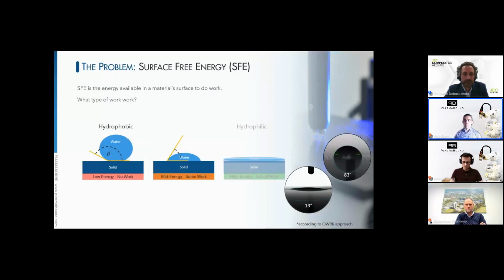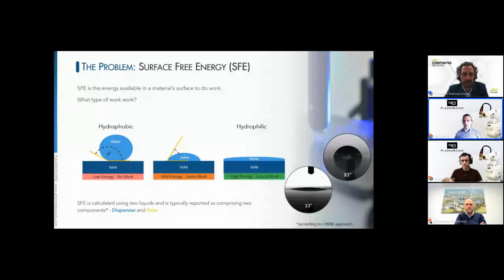Then in a hydrophilic system, where there's a high energy present at the interface, we will see what is called fully wetting out or full spread. That is, the water becomes drawn into that structure. For the purposes of the rest of this presentation, I'm just going to touch on one subject matter, which is the SFE and how it is comprised. So surface free energy, or SFE as it will sometimes be termed, typically comprises 2 components, according to OWRK. Folks believe that these components are considered to be dispersive and non-polar and polar, but in OWRK's case, they believe in the terms dispersive and polar because it matches up a little bit closer with the chemical functionalities.